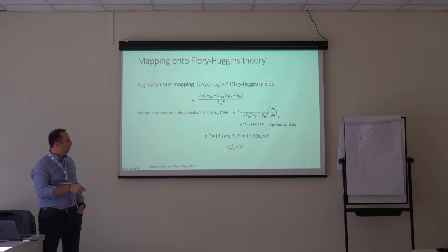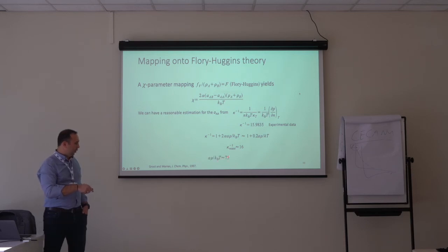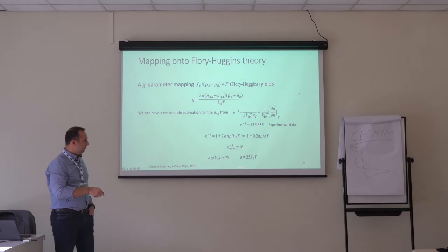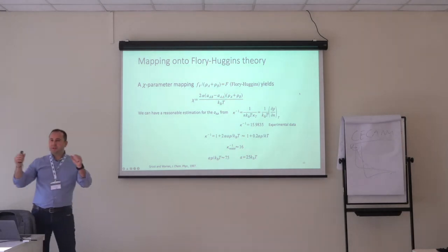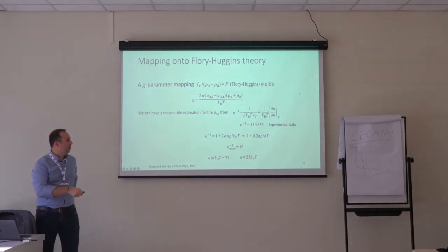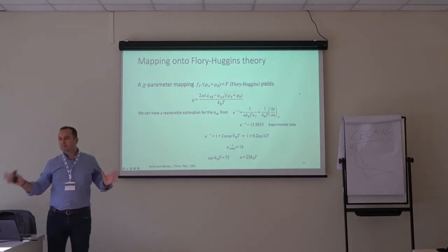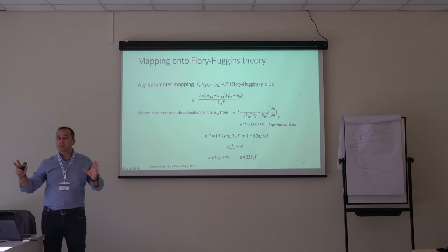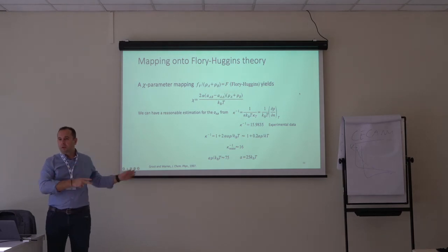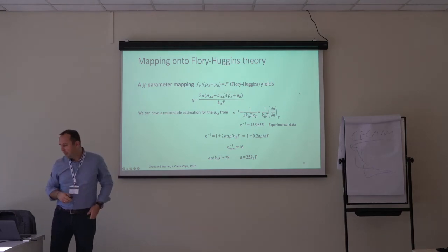And you know that it is approximately 16 for a number density of 3, and you get the like-like interactions, which means the same type of beads interact with 25 kT. So that is how it works if you are using water, where one bead represents one water molecule.